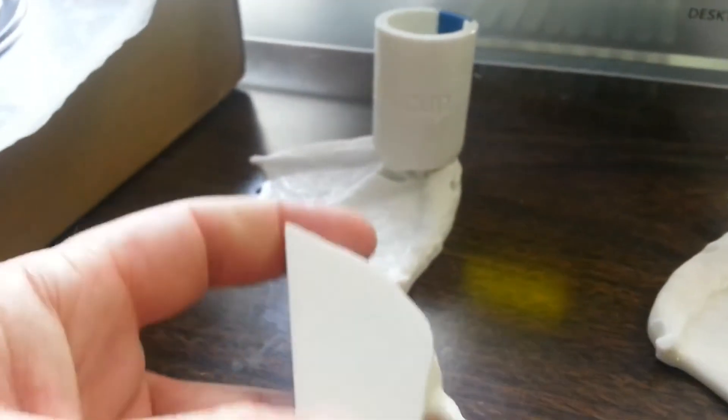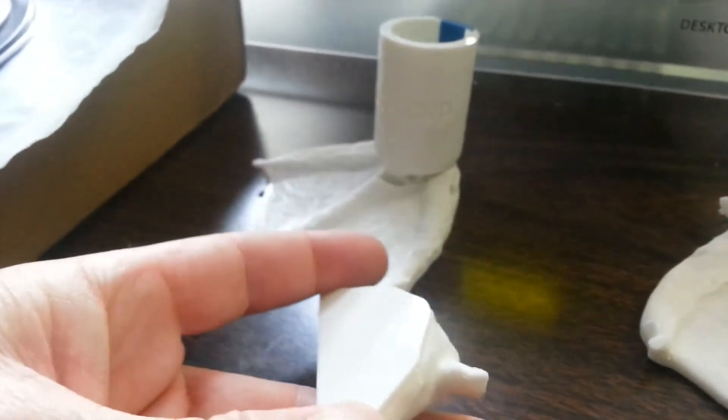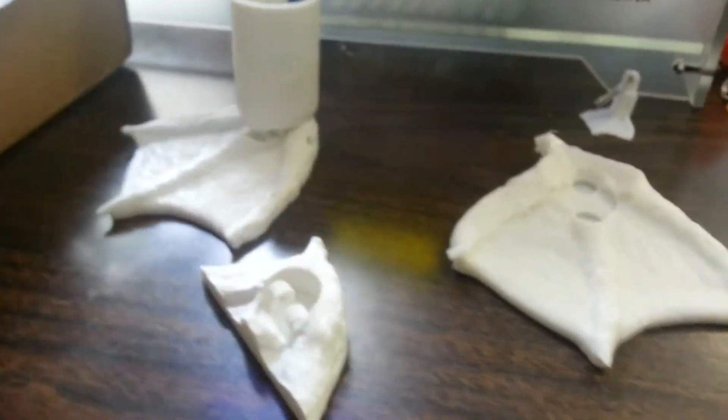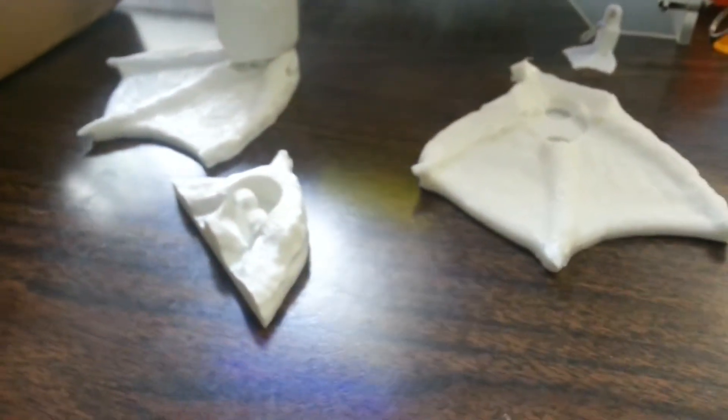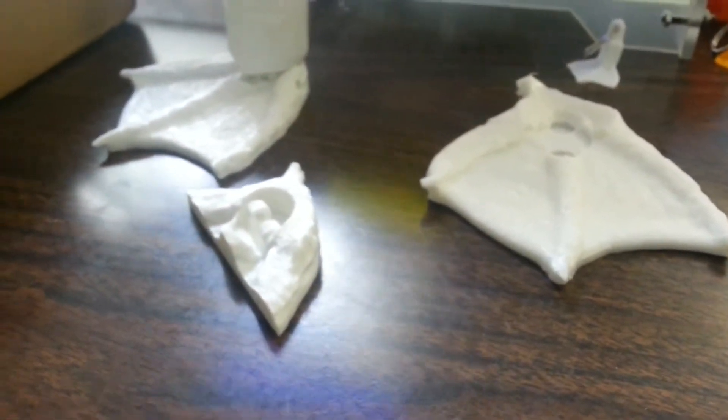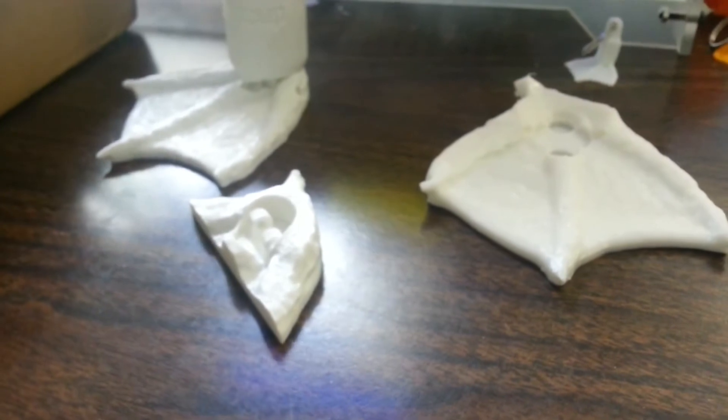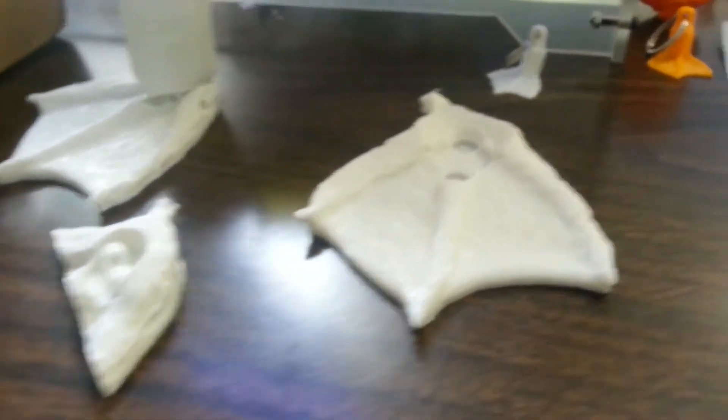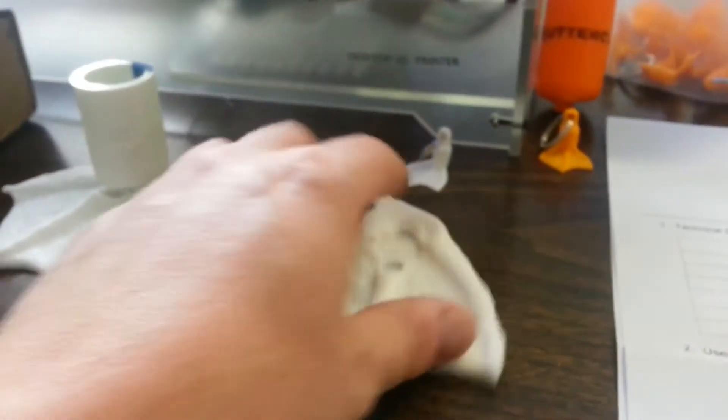It's really nice with a nice finish. I generally print at about 210 degrees for the Polymax and about 215 for the Polyflex. Now this is the bottom of the Polyflex.